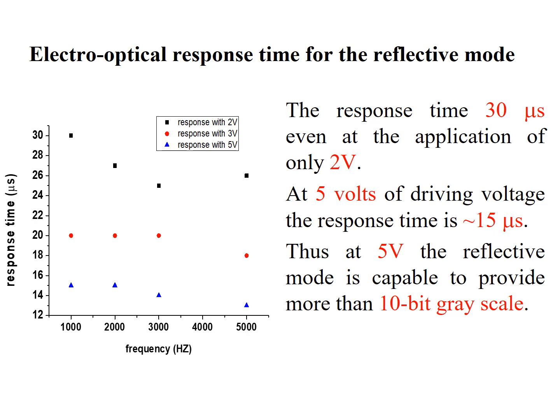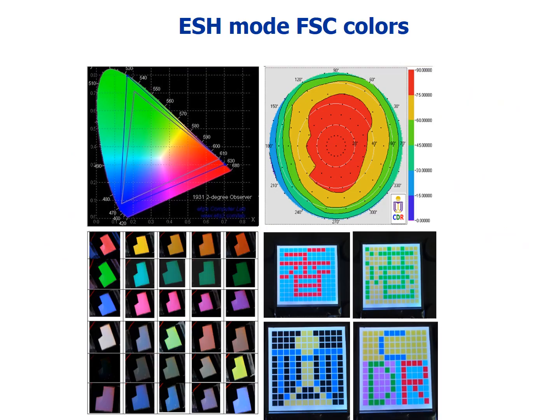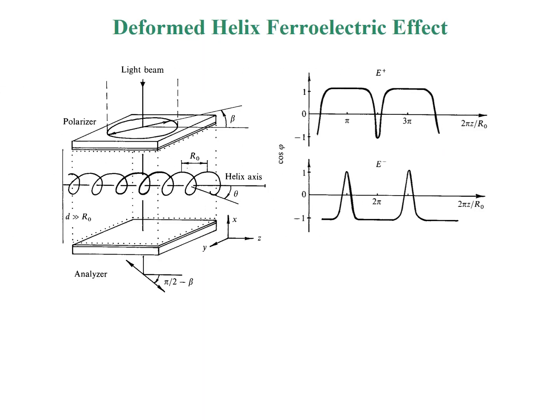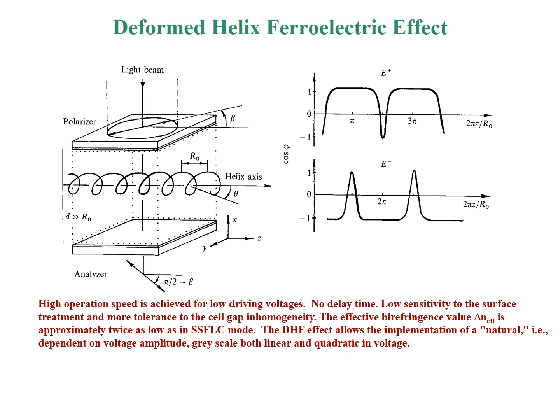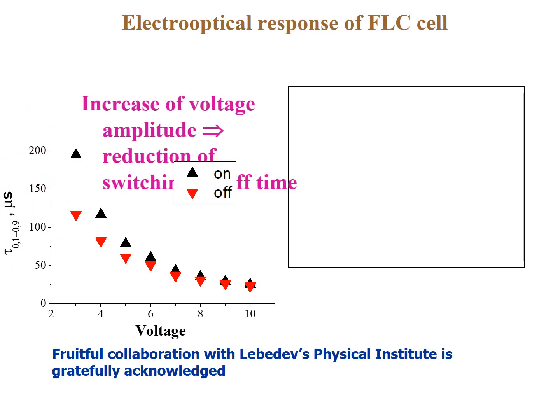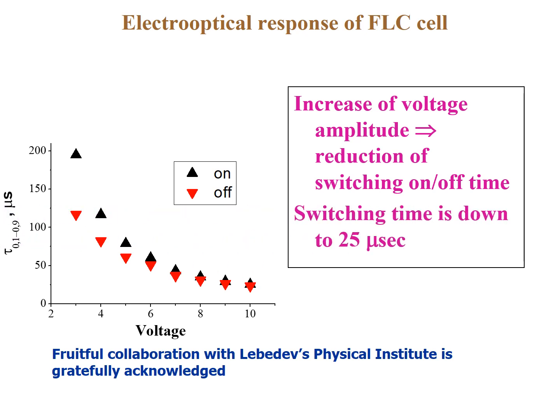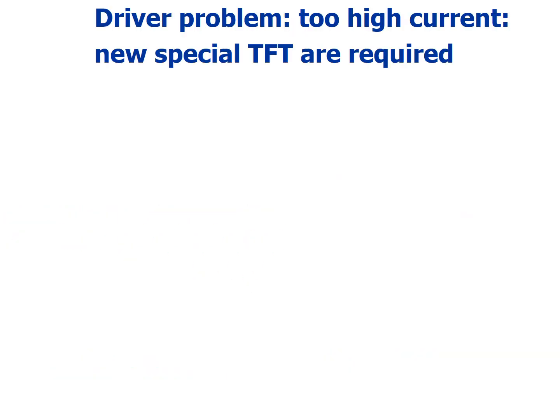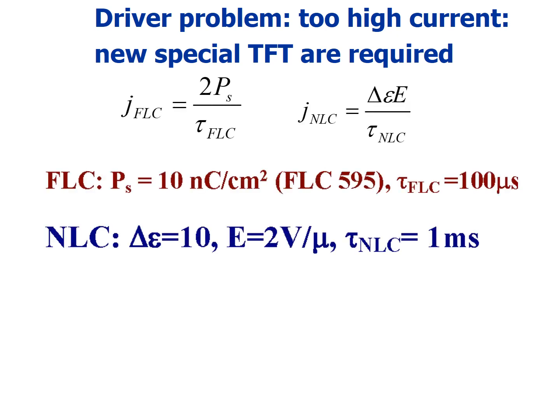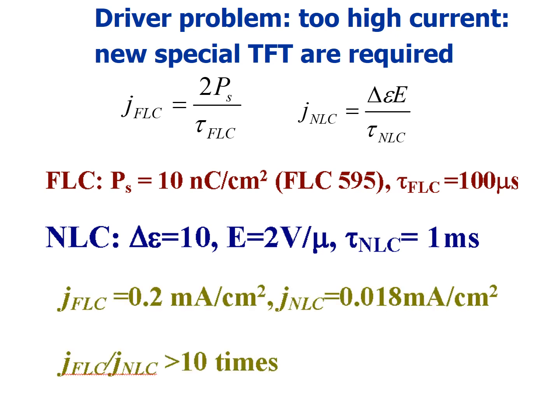So for reflective mode, we have 15 microsecond response time and many gray levels, and excellent viewing independence. So here is a display mode which we have mentioned colors, and we use different ferroelectric liquid crystal mode like deformed helix ferroelectric effect, and this mode can produce extremely fast response time, 25 microseconds. Easy to get. We also developed new thin film transistors, which enable us to operate with liquid crystal, because charging current should be much higher because of fast response time.